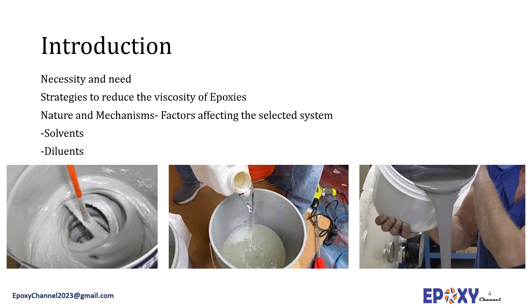Two distinct classes of diluents are used with epoxy resins: non-reactive diluents and reactive diluents. Reactive diluents will enter into the cross-linking reaction with the primary resin, while non-reactive diluents will not. Non-reactive diluents primarily act as low molecular weight plasticizers for the epoxy composition. Important factors for solvents and diluents in epoxy systems include evaporation rates, solvent strength, and dispersion power. The choice of solvent or diluent is made with regard to solubility, viscosity, drying times, and wetting characteristics required for the final product — all of which affect the bond performance of the resulting epoxy.